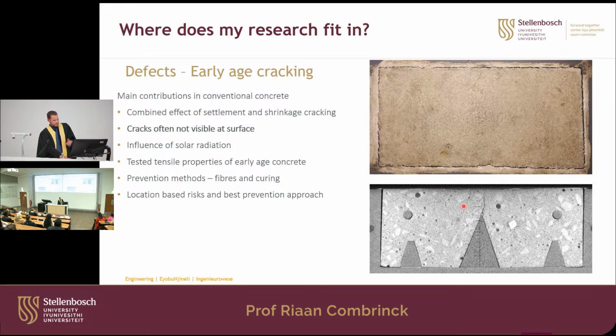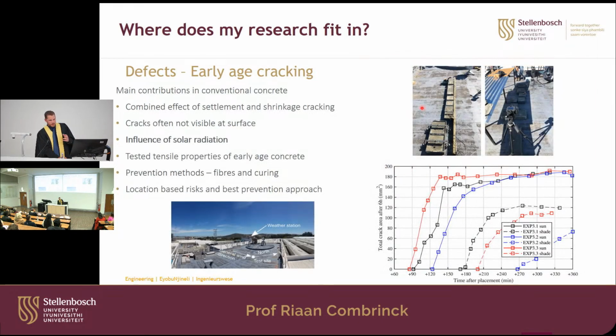Then the influence of solar radiation. If you test with and without sun, this is also very important, because most models that you use to predict evaporation don't include the impact of solar radiation. So we've done tests, some of the nicest tests we've done, with a view on top of the civil engineering building, with and without shade. You can see all of this is the crack area with time. These are all the concrete in the shade, and this is all the concrete in the sun. You can see the big impact it has just having sun on the same mixtures in the same environment, how much bigger the cracks are just with sun.